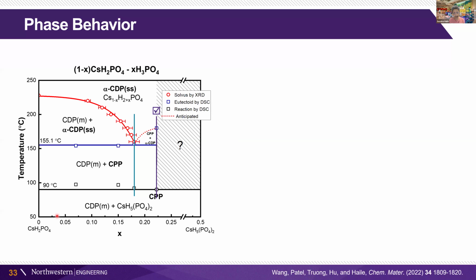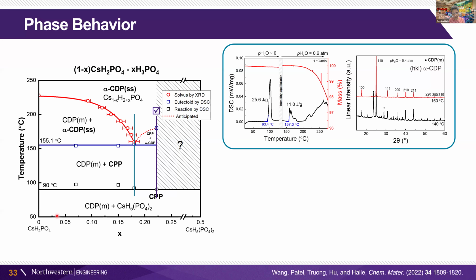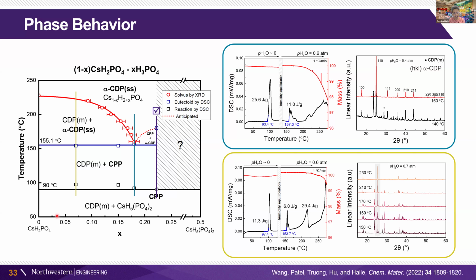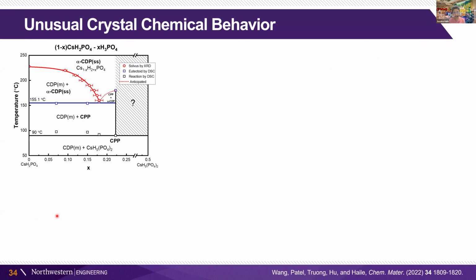that. And just to show you the diffraction results at the eutectoid composition, we clearly go to the cubic phase at very low temperature. This eutectoid transition is at 155 C, so we can see the cubic pattern forming at 160 C very nicely. And as we go to higher compositions of cesium, then we have this region here where we have a two-phase system, and the monoclinic cesium dihydrogen phosphate slowly gets consumed, and the cubic phase slowly increases in content. Okay, so this is our unusual phase diagram.